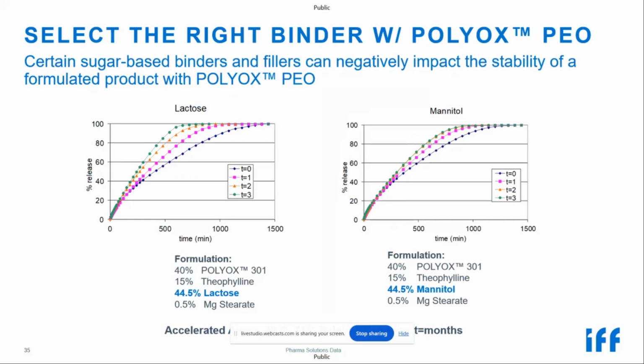We use this to understand the impact of binder selection in a POLYOX formulation. So here we took POLYOX 301, mixed it with theophylline, magnesium stearate, and different binders. On this slide, I'm showing lactose and mannitol. Put those on accelerated stability for up to 3 months and looked at dissolution. And with lactose, we see this rapid increase in dissolution rate over that storage time, which is indicative of PEO molecular weight decreasing over time and allowing for faster drug release. We saw something similar with mannitol, maybe not the same drastic effect as lactose. So these reducing sugars might be negatively impacting the stability of PEO within a tablet.